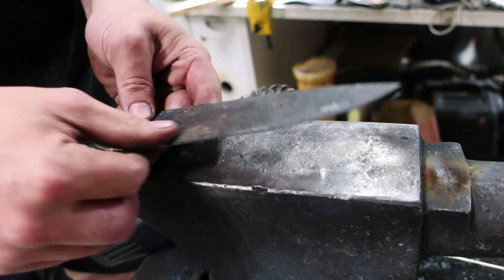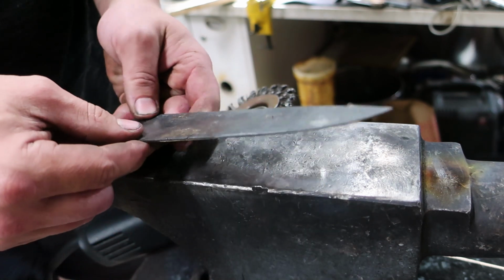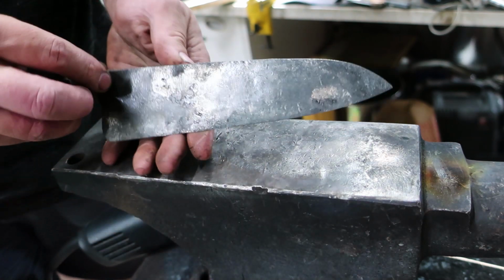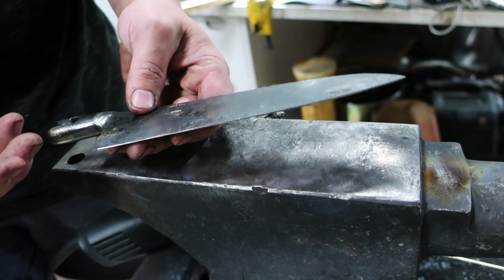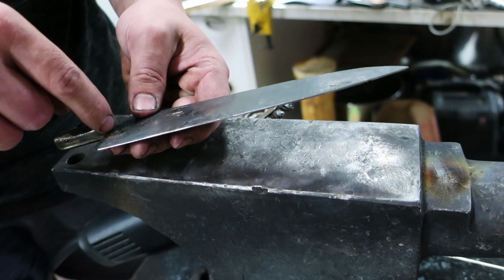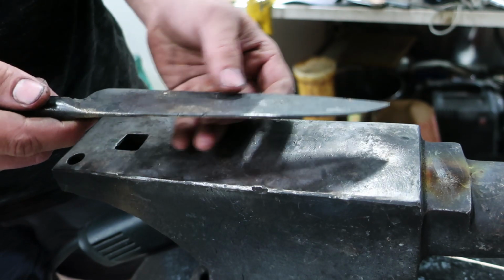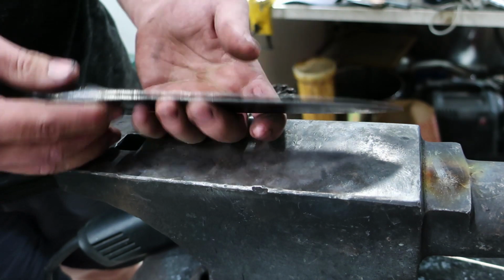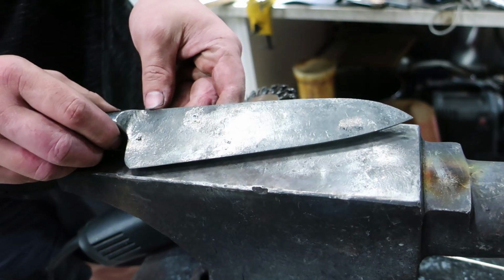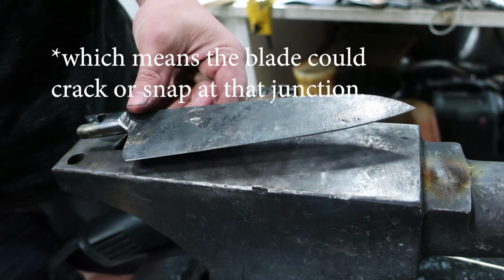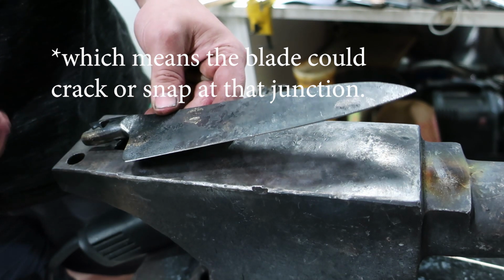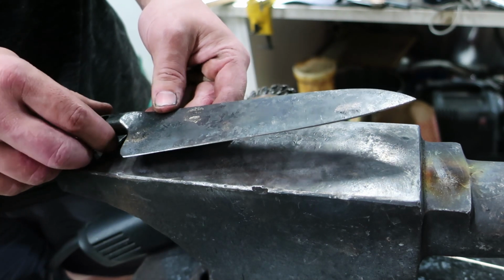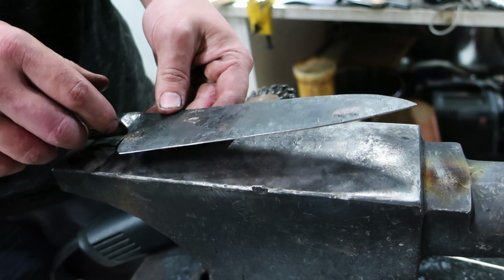So I had to forge and grind the knife a bit more, and I also did the bolster. I tried silver soldering the inclusions because I have a few worries. First, I don't like the idea of pits being in the blade where food can possibly get trapped and make it hard to clean. And also these inclusions are stress risers, which in all honesty, the silver solder didn't work. In fact, if it did fill the voids, it would probably just all melt out getting the temp in the kiln, which is now heating up.